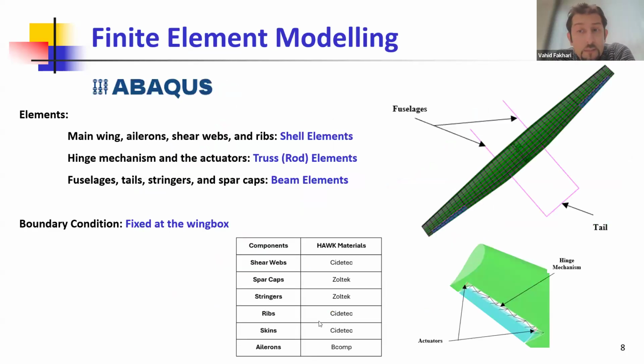We developed a finite element model in Abaqus based on the TU Delft model. In this model, the main wing, ailerons, shear webs, and ribs have been modeled with shell elements. The hinge mechanism and actuators were modeled with truss elements, and finally, beam elements were employed for fuselages, tails, stringers, and spar caps. The boundary condition was considered to be fixed at the wing box, and we used the novel composite materials in the HAWK project that Cormac explained in the previous presentation for the components, as shown in this table.